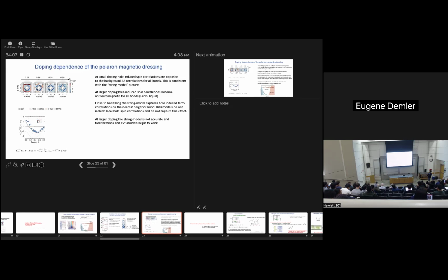On the other hand, we can take theoretical models which are more in line with traditional treatment, like RPA. But what's common for these traditional theories is that they assume that as holes move, they frustrate, they modify spin correlations on the average. It's not a local picture of spin configuration being distorted in the vicinity of the hole, but really on the average.